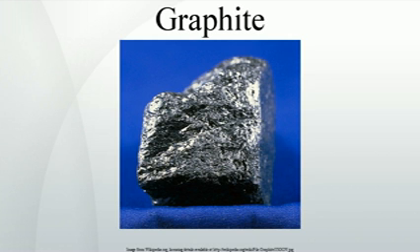Graphite mining, beneficiation, and milling. Graphite is mined by both open pit and underground methods. Graphite usually needs beneficiation. This may be carried out by hand-picking the pieces of gangue, rock, and hand-screening the product, or by crushing the rock and floating out the graphite. Beneficiation by flotation encounters the difficulty that graphite is very soft and marks, coats, the particles of gangue. This makes the marked gangue particles float off with the graphite, yielding impure concentrate.